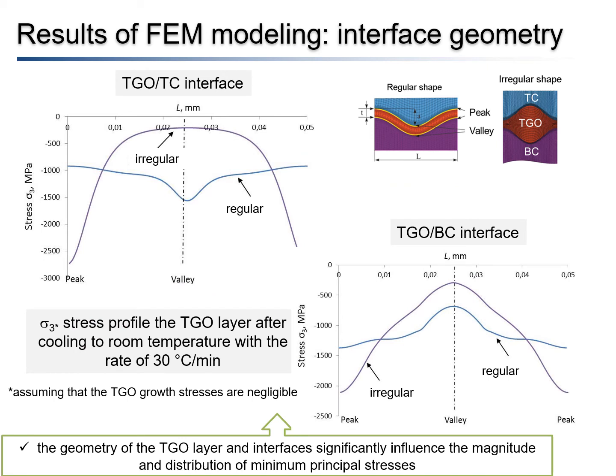In contrast, the result of finite element methods modeling shows that the geometry of the TGO layer and geometry of interfaces significantly influence the magnitude and distribution of residual thermal stresses.